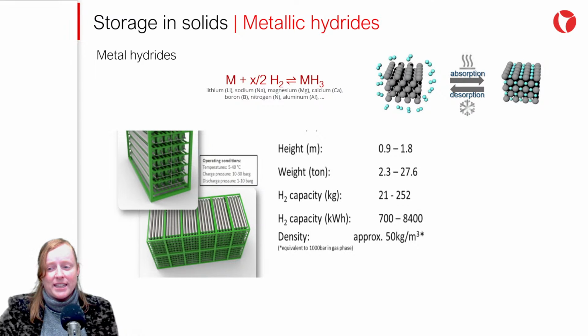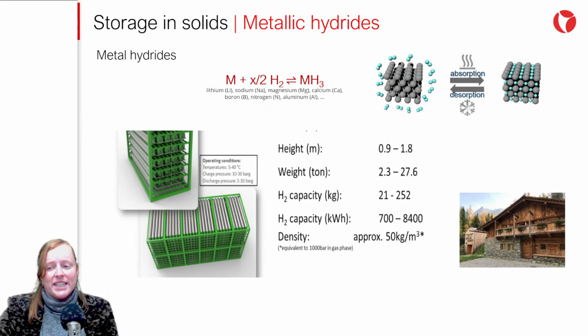The biggest drawbacks that this solution faces are the high temperature necessary to release the hydrogen, at around 300 degrees Celsius, the relative slowness of the absorption-desorption processes, and the degradation due to repetitive charge and discharge cycles. Its application is studied and developed for use in vehicles, homes, and buildings due to the safety offered by this storage, this solid and stable storage.